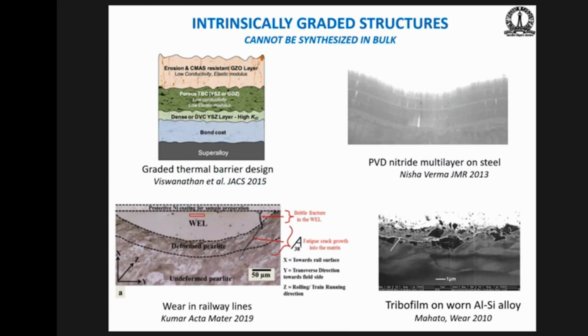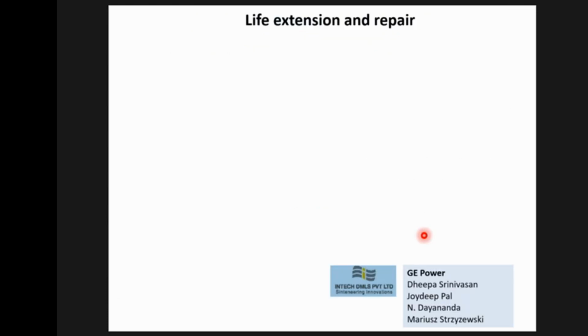You also have length scale issues or the need to test small samples when you have coatings or surface damage layers. These could be in thermal barriers or PVD coatings. In the case of these tribological layers that form on railway lines, the mechanical properties of the regions which determine wear or fracture are very small, and so you need to know what they are. Or in the case of a tribofilm on an aluminum silicon piston. So that's one class of systems where you need to find ways of testing small samples.